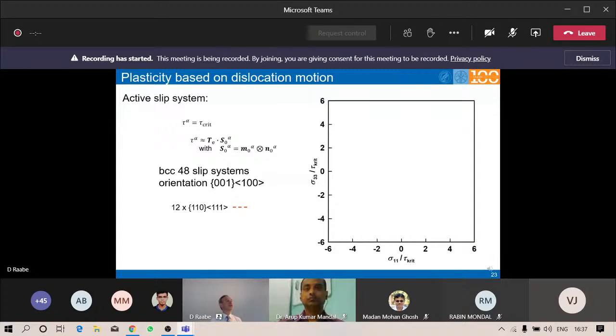And you can calculate this into a two-dimensional section of the otherwise five-dimensional convex yield surface of a single crystal situation, and then plot these kinematic bounds where you activate certain slip systems as lines. So the red dotted lines that you see here indicate when your arbitrary stress tensor projected into this 2D slice here reaches the critical stress to activate a certain slip system.